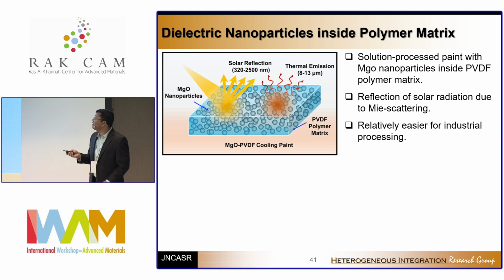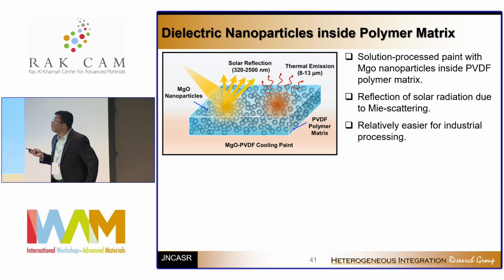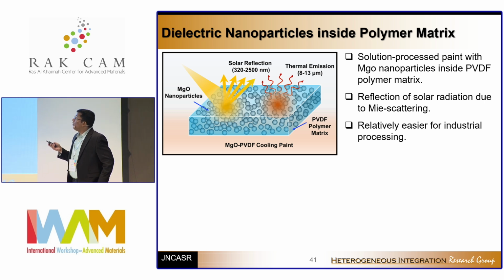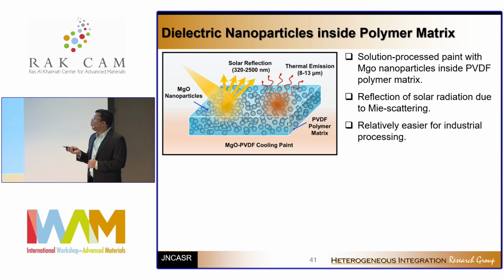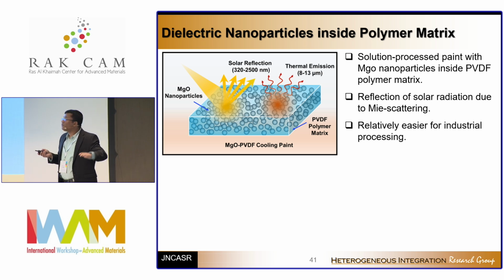But the solution that we came up with is basically nanoparticles of a dielectric, for example MgO, made into a nanocomposite with a polymer matrix. So MgO PVDF polymer matrix. This is basically a polymer matrix between MgO and PVDF. You can solution process it, spin coat it on any surface and substrate that you are looking at.